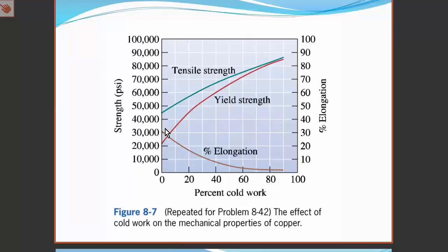First, we may heat treat the material to put it into a standard state, which we will call zero cold work, in an annealed state. If we want to increase the tensile strength, we can cold work it to the appropriate amount to get that final tensile strength. Obviously, we will have to start off with the larger diameter or cross-sectional area, so that when we reduce it to get the required amount of cold work, we reach the required shape. Of course, if there's a constraint on the percentage elongation, we have to make sure that we don't cold work too much, otherwise we lose the ductility and may go below specification.